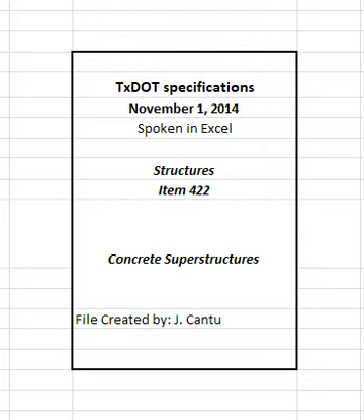3.8 Spraying equipment. Use mechanically powered pressure sprayers with appropriate atomizing nozzles for the application of membrane curing. Mechanically driven spraying equipment, adaptable to the rail system used by the screeds, may be used for applying membrane curing to bridge slabs. Use hand pressurized spray equipment equipped with 2 or 3 fan spray nozzles if approved. Ensure the spray from each nozzle overlaps the spray from adjacent nozzles by approximately 50%.